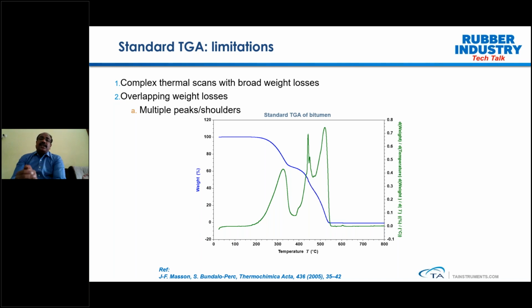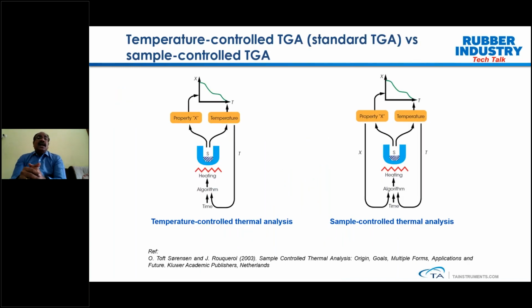So here comes the advanced mode called high resolution TGA, which is basically a sample controlled TGA. One should understand the difference between a temperature controlled TGA and a sample controlled TGA. In sample controlled TGA, we are regulating the heating rate based on the decomposition nature of your sample. If you look at the left hand side, here we define the heating rate. So irrespective of sample decomposition or weight changes, the TGA is going to ramp up the temperature at the predefined heating rate. Whereas in sample controlled TGA, as you can see on the right hand side, your sample weight loss is also a part of your control algorithm.